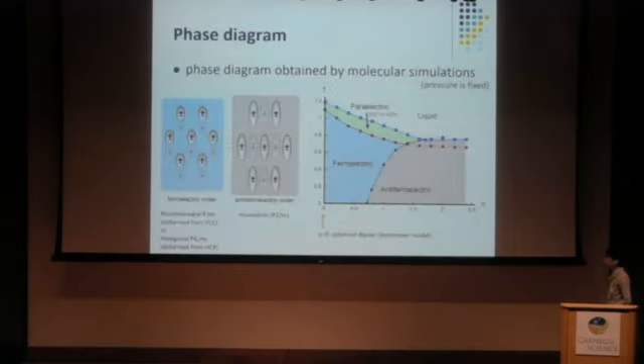So this is the phase diagram of our model. This is the most important figure in my talk. We change the particle anisotropy eta, which corresponds to changing the particle shape, and we change the temperature. So there are three crystalline phases: one is paraelectric, one is ferroelectric, and one is antiferroelectric.